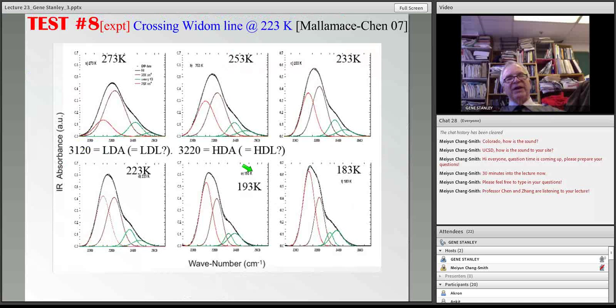Here's one of the things they found out. They found out that when you make measurements, now this temperature is well below the homogeneous nucleation temperature. You can see if water melts at 273, and so here's water at its melting temperature, bulk water melting temperature, and what you see is the intensity of infrared absorption as a function of frequency. The black curve is the full sample, and as you can see, it's a little asymmetric.